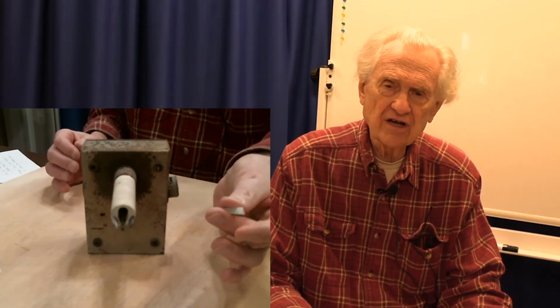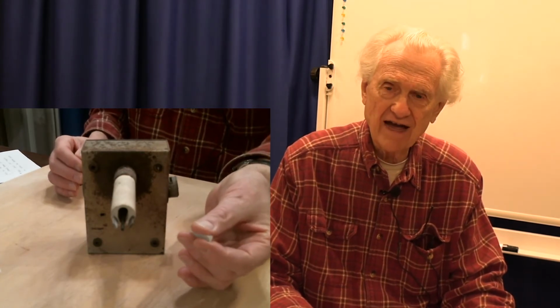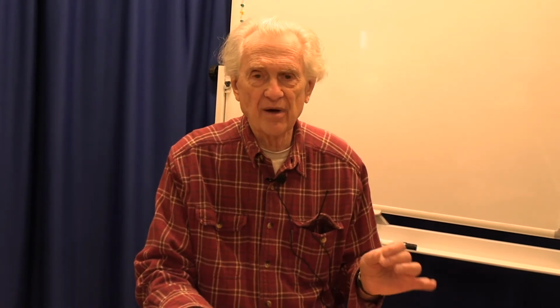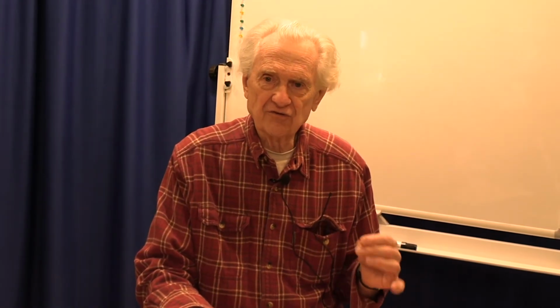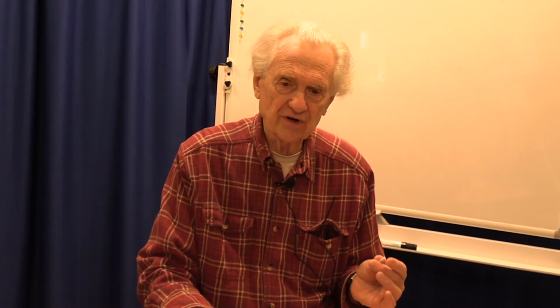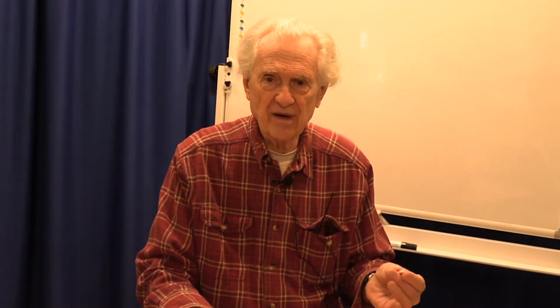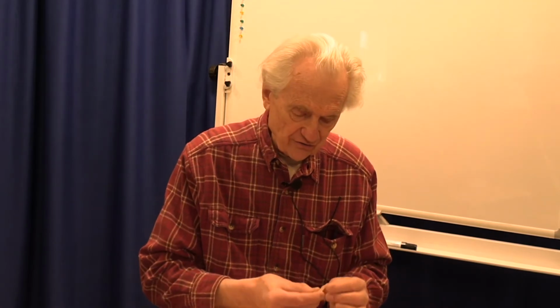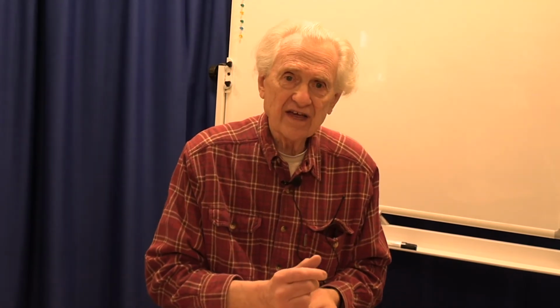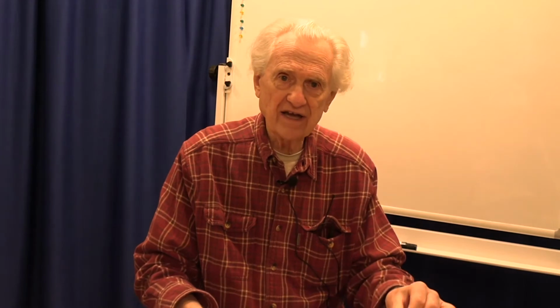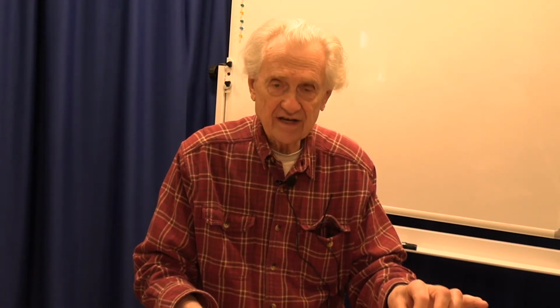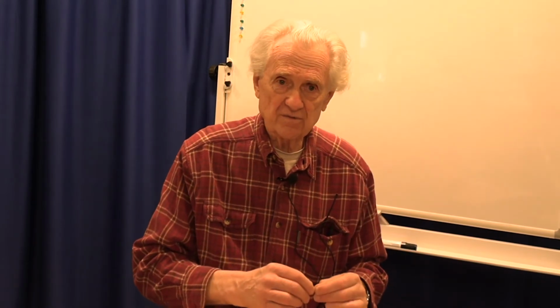What you're doing is you're looking for cracked cones. It's not uncommon for a cone to have a crack in it where the tip will break off or it'll break in half. Cones are made by pressing mixtures of dry powders into a mold or into a die, and there's no way to really inspect them if they have cracks or defects in them. And the problem is if you're using it to control a kiln sitter, then if it has a crack in it, it can break and crack, and the kiln sitter will shut off prematurely, and so your firing is premature.